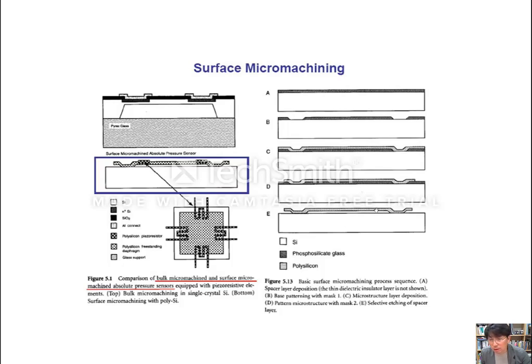Over here, you see certain empty space, so you need to fill it with certain material, and then you need to remove it. So we start with a sacrificial layer deposited, in this case phosphosilicate glass, and then you pattern it and make openings to make an anchor for this polysilicon mechanical structure, the polysilicon diaphragm here. And then this glass is removed to make a space so that this diaphragm can vibrate. And then with an additional process you can make this polysilicon piezoresistor to measure the deformation of this diaphragm.